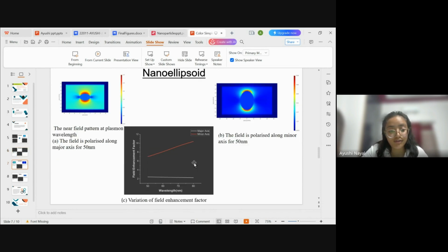Then the first graph is for the field enhancement pattern when the field is polarized along the major axis for a 50 nanometer nanoellipsoid, and B for when the field is polarized along the minor axis for a 50 nanometer nanoellipsoid. The variation of field enhancement factor: as you can see, there are two lines, one for the major axis and one for the minor axis. The major axis has values more than the minor axis.